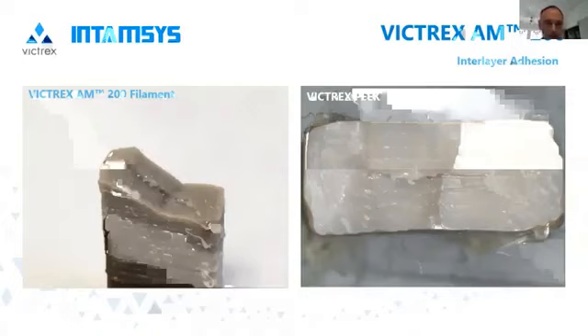And as a consequence of that, we're seeing improvements in the performance of printed parts. On the right-hand side, you can see a shiny area, which is a flat fracture surface on the PEEK sample. And this is where it delaminated partially along the interface between the printed layers. So it's a consideration for your choice of material, depending on the job and the part that you're making, but it obviously depends upon the key end user requirements and the demand placed upon that end part.